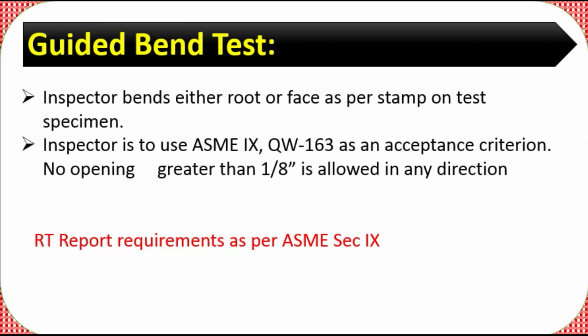The inspector is to use ASME Section 9 QW163 as an acceptance criterion. No opening greater than 1/8 inch is allowed in any direction. So the inspector will check the guide bend test, the face bend test or root bend test, as per QW163 of ASME Section 9. If any opening is more than 1/8 inch, then it will be a defect and it will not be acceptable.